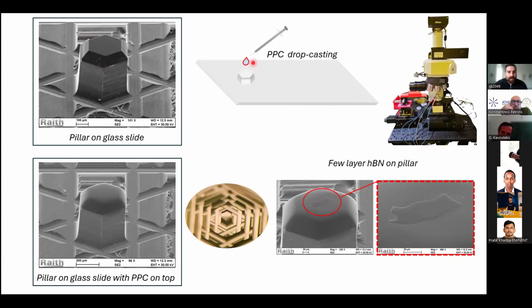So I will go then and put my polymer on top, and then implement this on a fully motorized, automated, custom-made transfer setup that we have here. So the polymer will conform to the surface of the pillar like that. And it can be easily then used to pick up flakes, as you can see here. This flake is around 70, 80 microns. So you can understand that I have high selectivity in the process here. And the flake sits on the surface of the polymer.